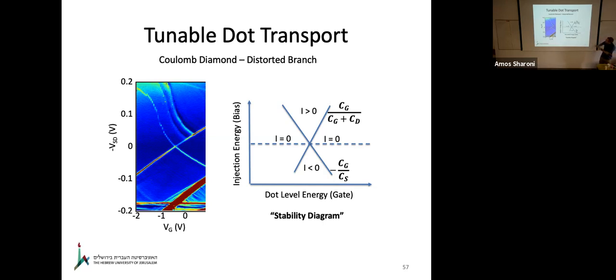If it's just a simple gating, you'd have 2 straight lines, but this line is crooked because the density of states of graphene varies with the gate. So the answer is yes, of course. It's not a superconductor. By the way, that particular device that David has built, the barrier is relatively thin. We try to build devices with thicker barriers. If you have thick barriers, you suppress the direct tunneling and you remain with the dot-assisted tunneling, and then that problem would not occur.